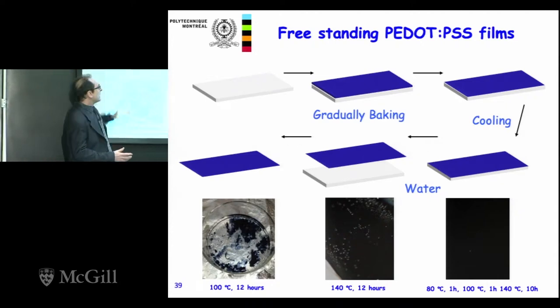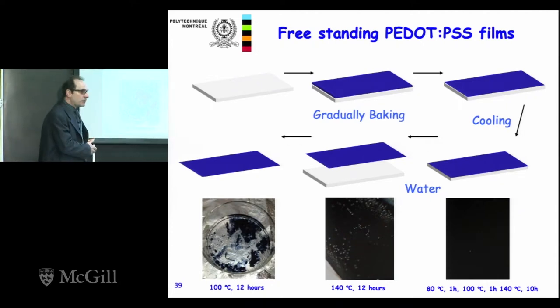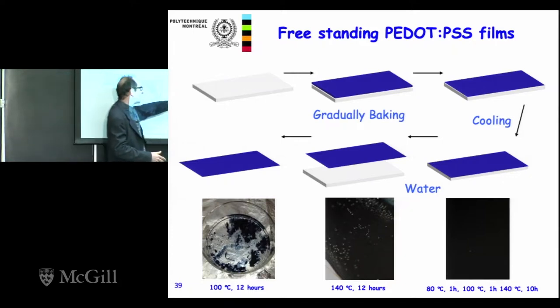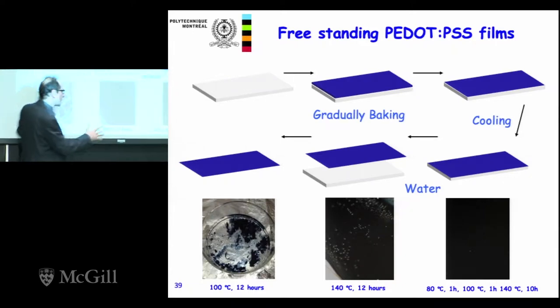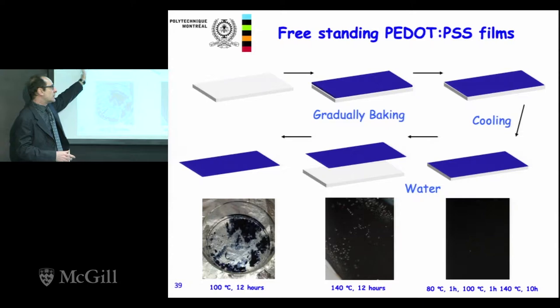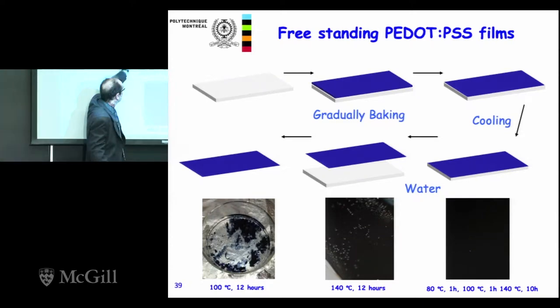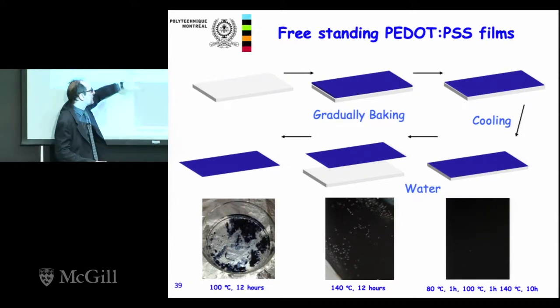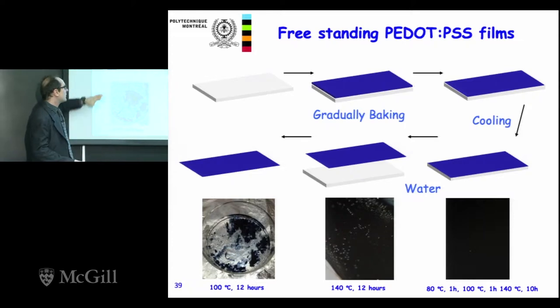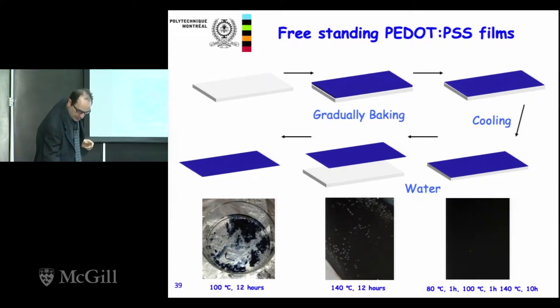First thing was how to make a freestanding film. So we developed, again, a process to make films which are self-standing. It's just a matter of time to bake the film, cool it, and immerse it in water. But finally, we have a procedure to make this.